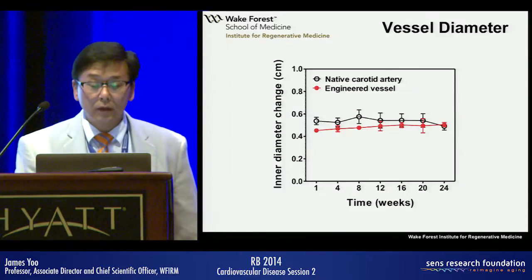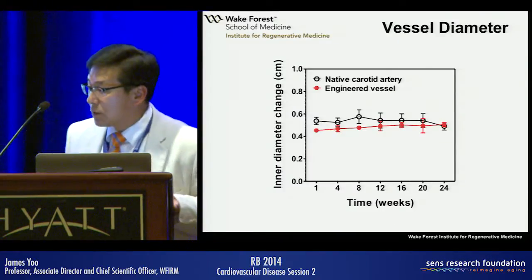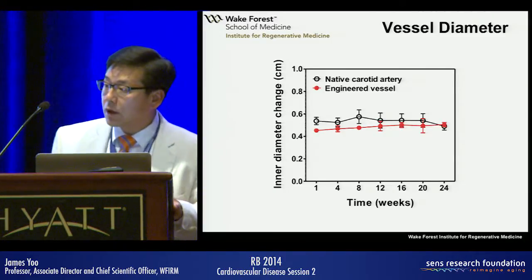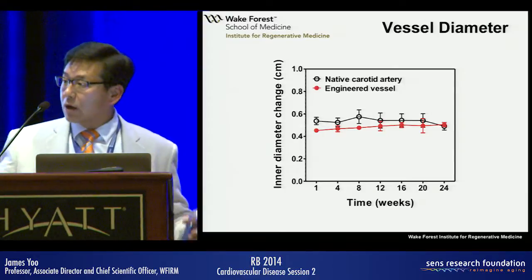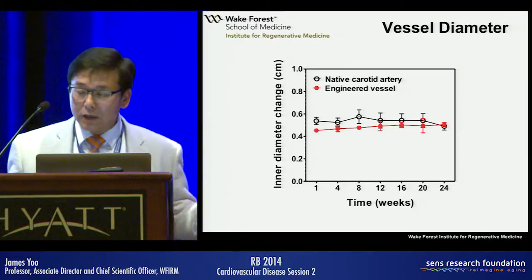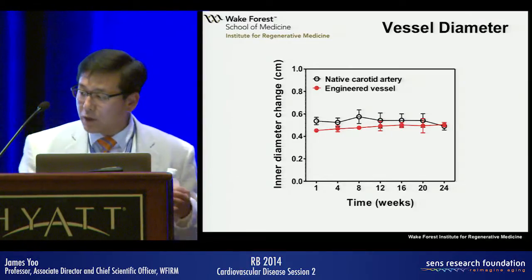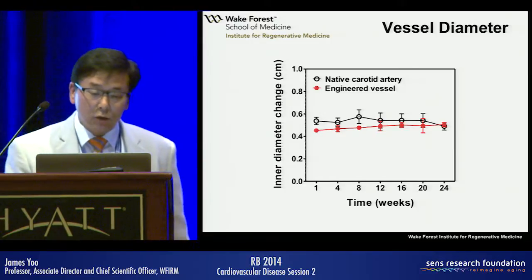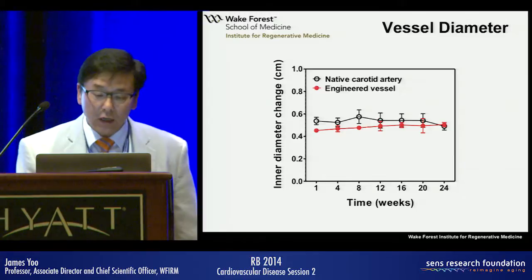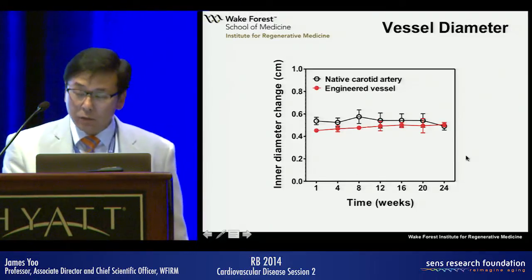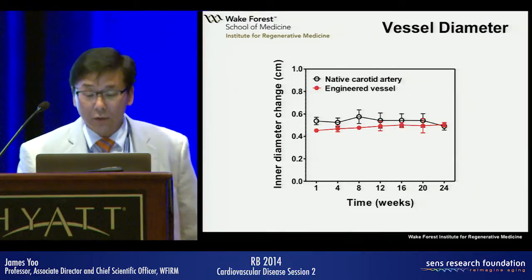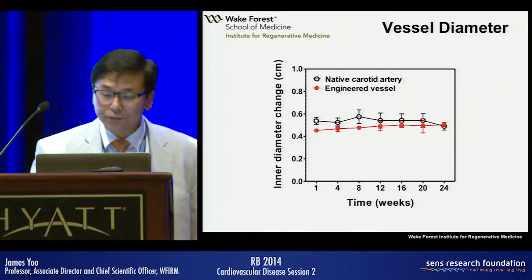Okay. So we looked at the vessel diameter because sometimes when you use a graft, the construct would contract or fibrose, scar down, or because of the pressure and flow, it may dilate. So we compared the engineered vessel with the native, and we were able to see pretty consistent size of the diameter for up to 6 months here.